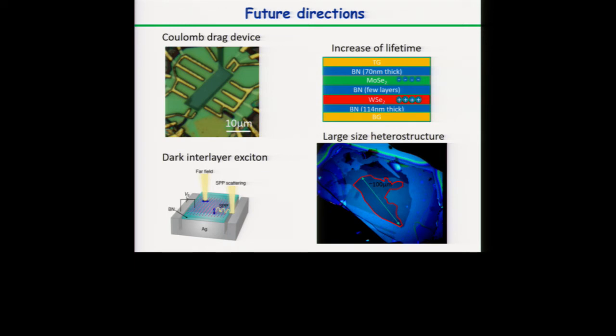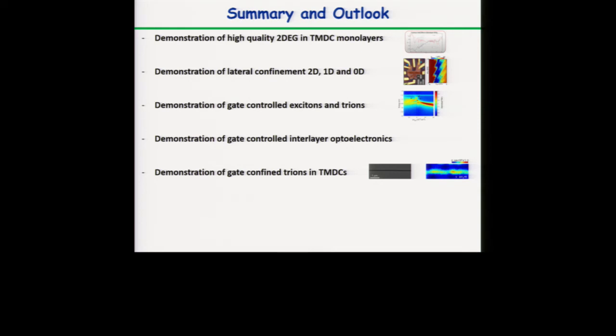We can also couple surface plasmon polaritons on silver to the heterostructure, and maybe we will be able to see the dark interlayer exciton, which also has an out-of-plane component. If we want to see large diffusion in these samples, we're also looking at making bigger samples. We can now make exfoliated heterostructures with sizes of around 100 micrometers. The exfoliation process here is different. It's a little bit more dirty, but we have measured one of these structures, and we obtain interlayer excitons. It's a little bit broader, but we can still obtain it in these large size heterostructures.